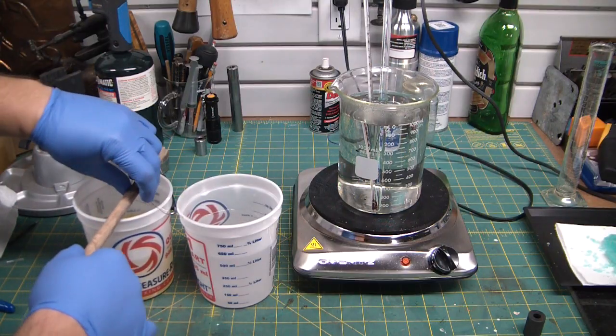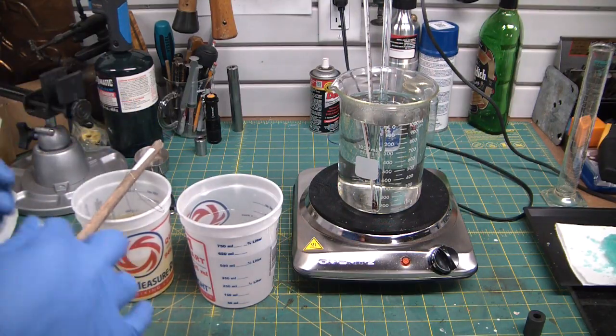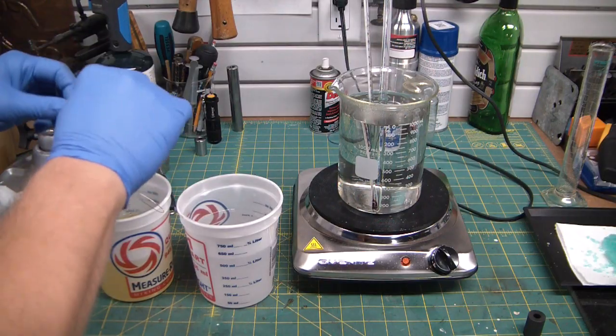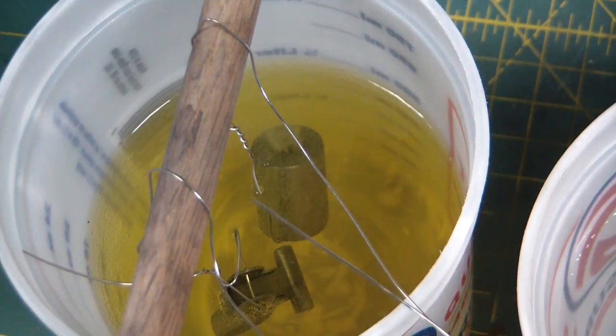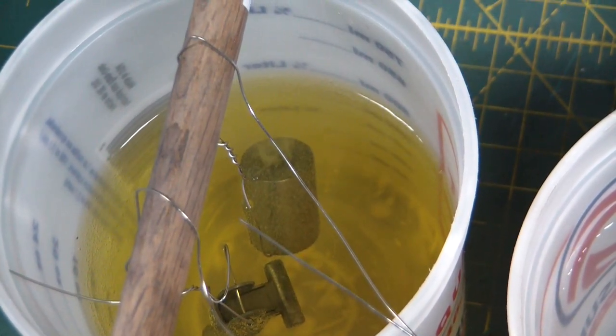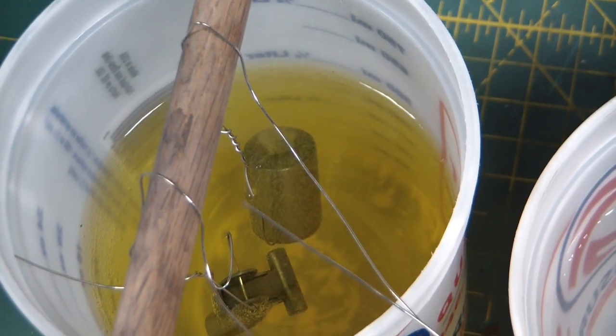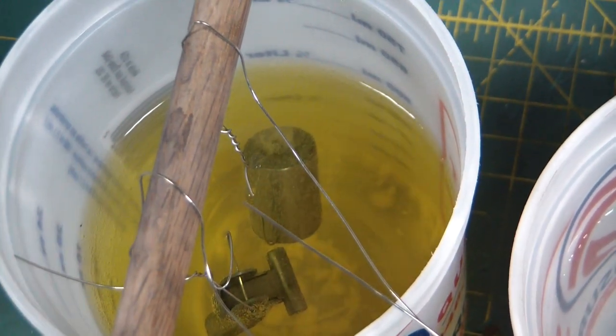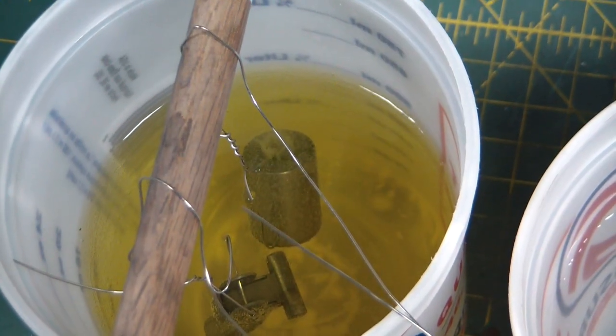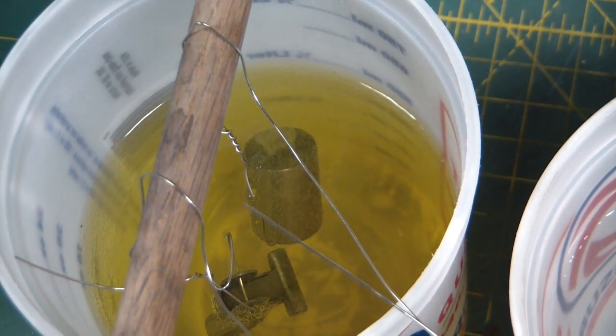Let me actually hang that on... I don't want it going uneven. I'm gonna throw another part in there for me. So here we have the steel parts just bubbling away in the citric solution, just lightly etching that surface, creating the little nucleation sites we want for the parkerizing to really bite into.